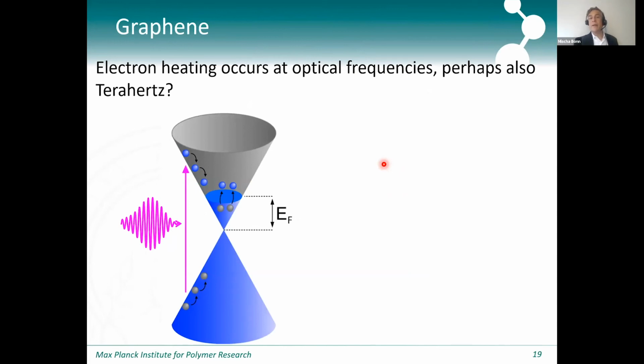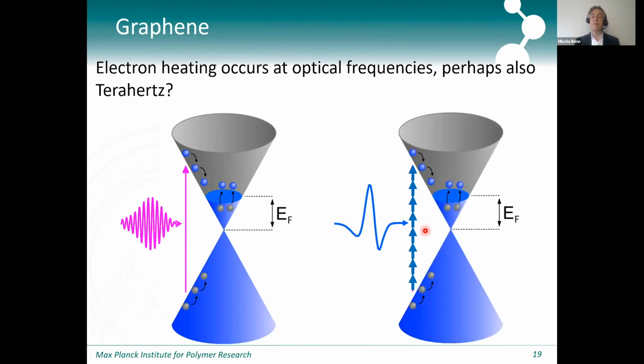So the question that I now have is, if this electron heating that we can induce with optical pulses also happens when we do the experiment with terahertz pulses, where you could imagine, I mean, a very extreme case is where we have some multi-photon terahertz excitation and we achieve the same state here. But one could also imagine that we simply heat up the electrons with the terahertz pulse. And would that also reduce the conductivity and the mobility of the samples of the graphene?